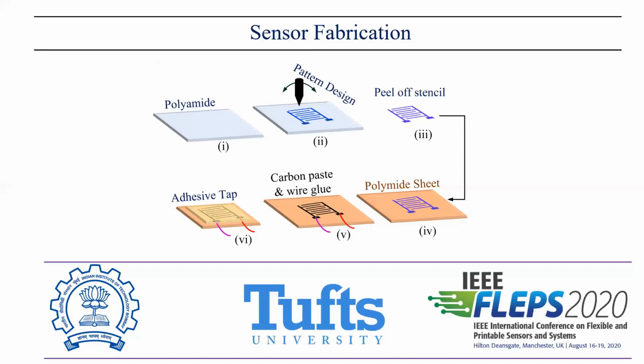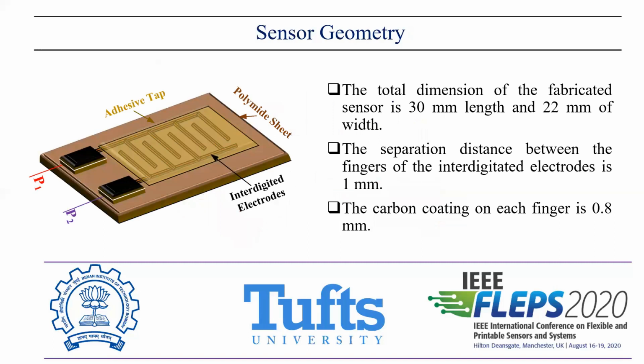So in this way, if there's a water level or soil moisture on top of the sensor, the fringing field between those electrodes will change, and this will change the capacitance of the sensor. In this way, we can measure the water level or the soil moisture across the sensor. This can be represented very well in this diagram, where this is a polymer sheet, and we have fabricated a pattern of interdigitated electrodes using a screen printed method, and then an adhesive tape was placed on top of it, and two electrodes were taken out for the connection